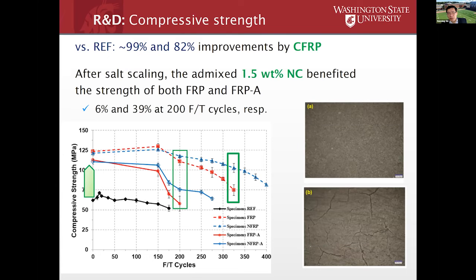Well, part of the reason is when we look at the cured epoxy adhesive under the microscope, you'll see A is the one nanomodified, which is very dense and crack-free, and B is the one without nanomodification, and it's not as homogeneous and it has some macro cracks.